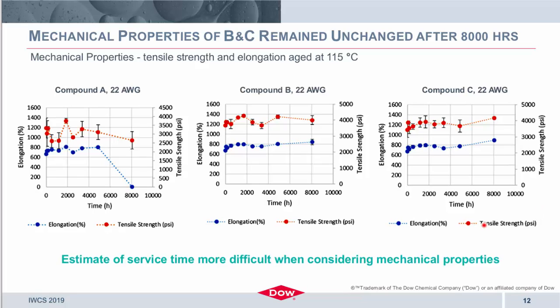For the thinner wall 24 gauge samples, they all performed in a similar fashion, but did fall off at shorter aging times, as you can expect from the thinner insulation layer. And we'll come back to that in a second.